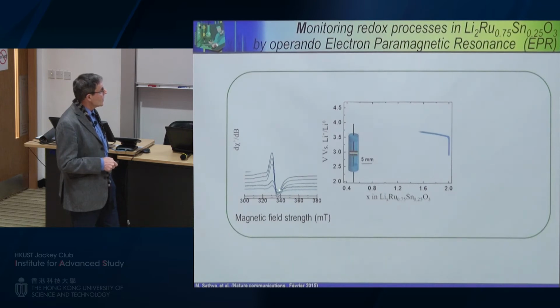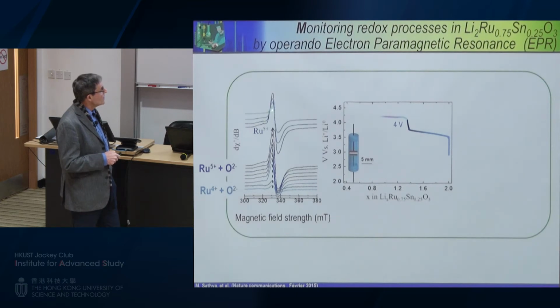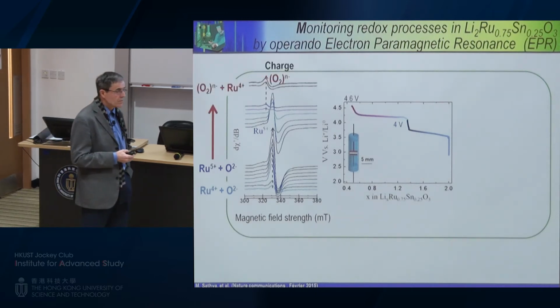And you can see we start with the featureless spectra, then the ruthenium 5+ is appearing, as clearly indicated there. If you follow the charge, you can see that the peaks disappear at the expense of another one, which here is directly related to this peroxo-like species.